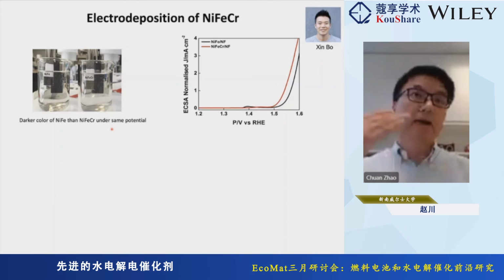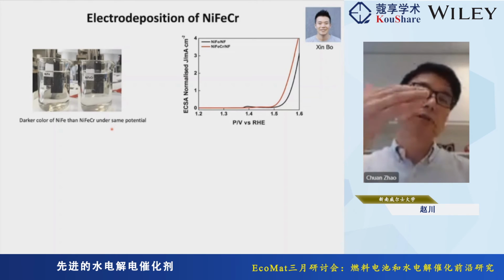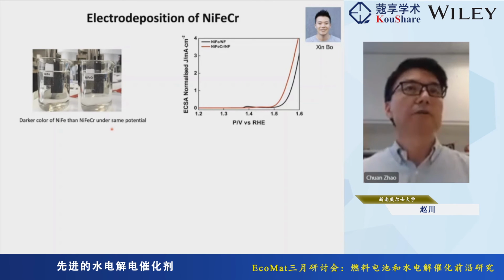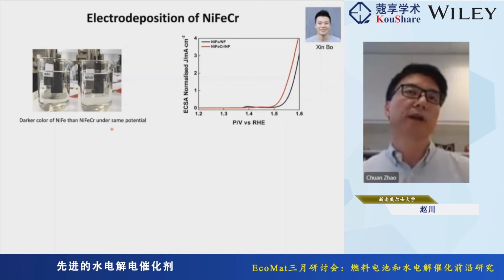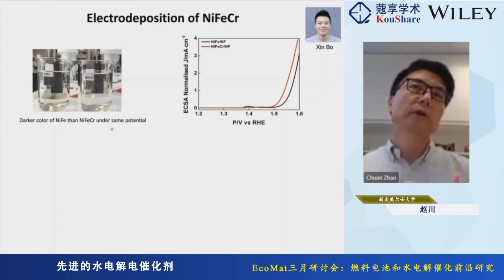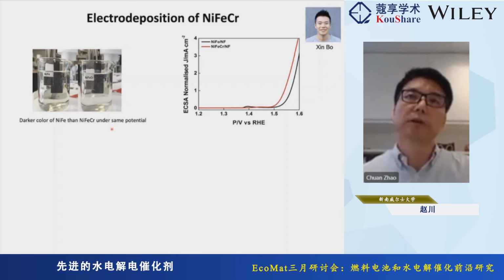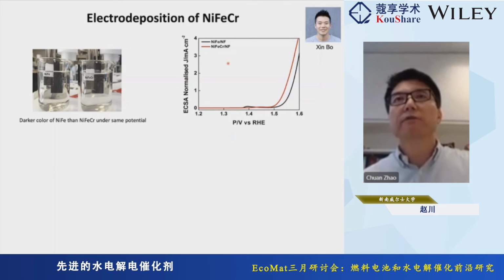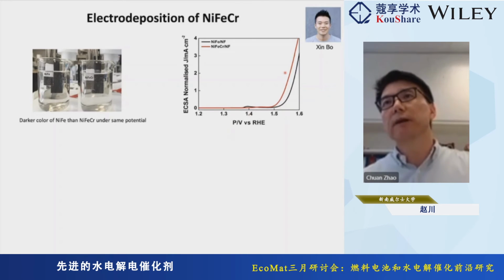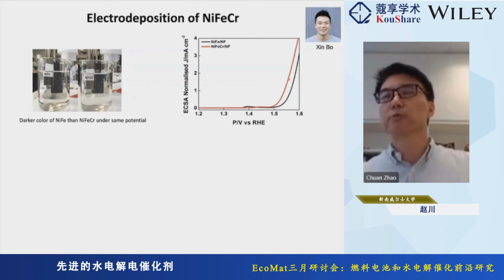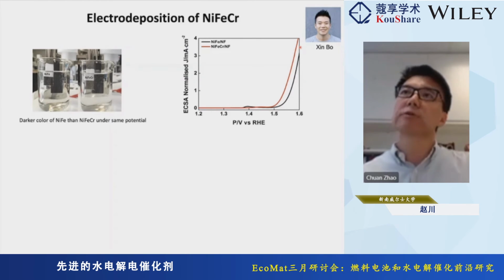We know that a higher oxidation state of nickel usually gives us a dark color. So that gives us the impression that nickel directly, during the OER, maintains a relatively lower oxidation state. And then the OER performance showed clearly a synergistic effect. After adding chromium, we get improved OER performance.